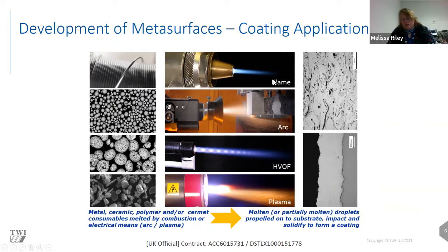The most basic is flame spray technology, which is basically a wire or powder consumable with a single cylinder of oxygen and a fuel gas. Depending on whether it's powder or wire will influence the coating quality. But powder-based processes are a lot more porous, and you tend to end up with a microstructure that looks a little bit like this. And that's similar as well to an arc sprayed coating, where you've got two consumable wires, you generate an arc between them, and then compressed air propels those droplets onto the substrate.